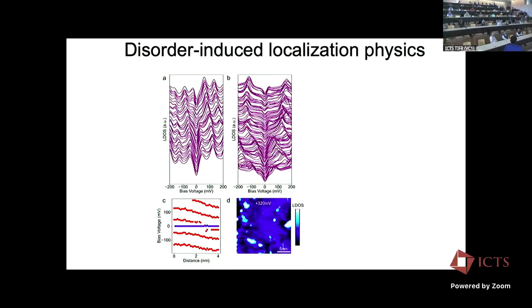Just a question about a clarification. When the modes are combined to miss a site or miss a group of sites, what's making them do that? What is the actual impurity? In the decorated, in the material, what is the defect? You just said defect. In this two-dimensional case? Yes, there's no additional defect. No, in the earlier one. The previous one. First, the vacancy produces states. So the vacancy, it's literally a vacancy? Yeah, a hole. Literally. Not a different atom, like when you put in another atom that gives you Kondo.